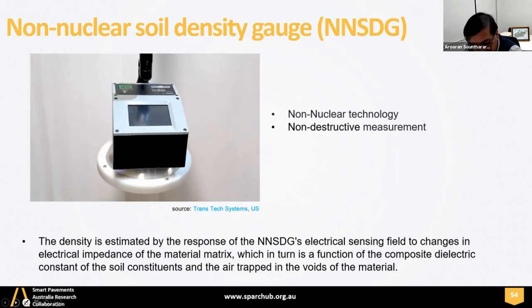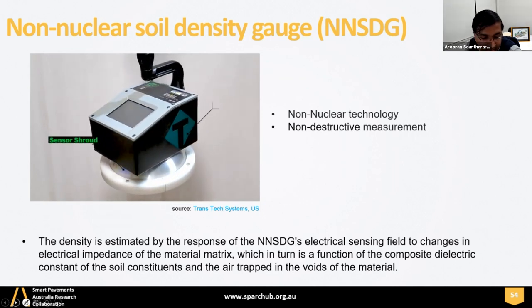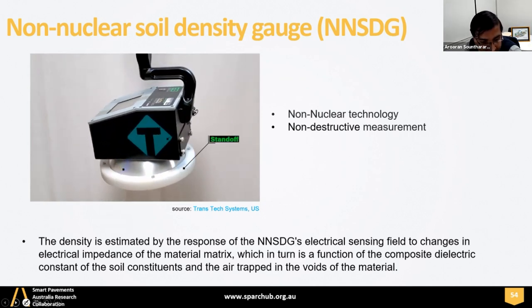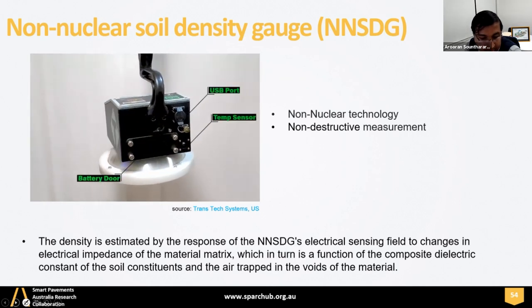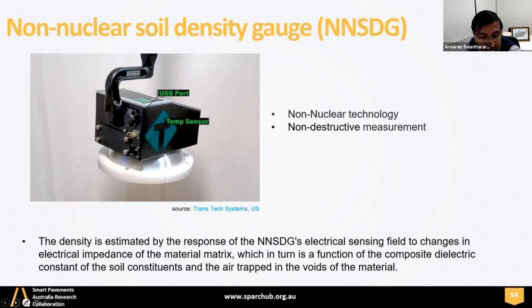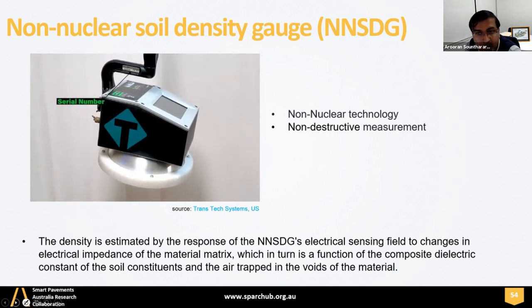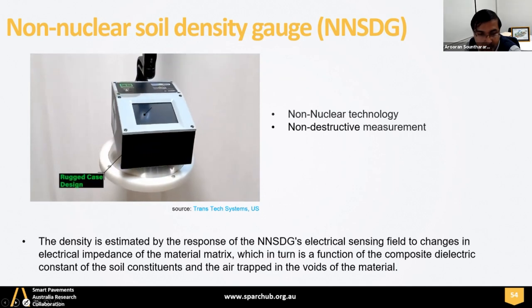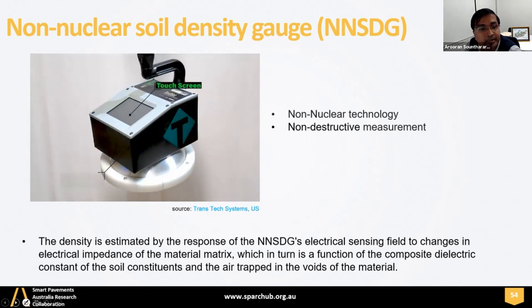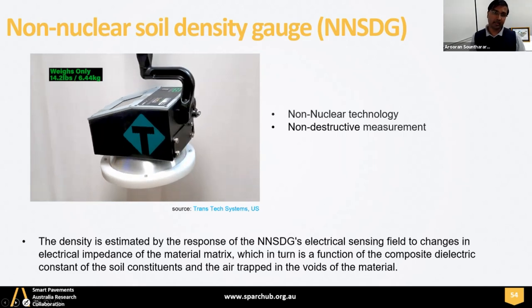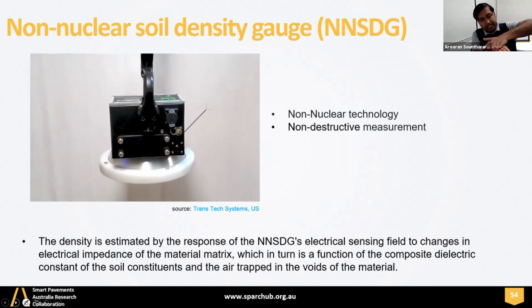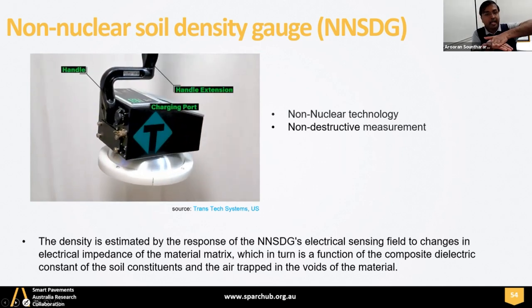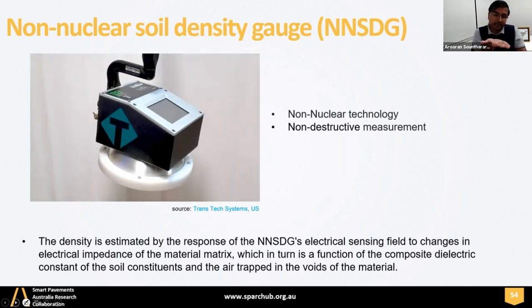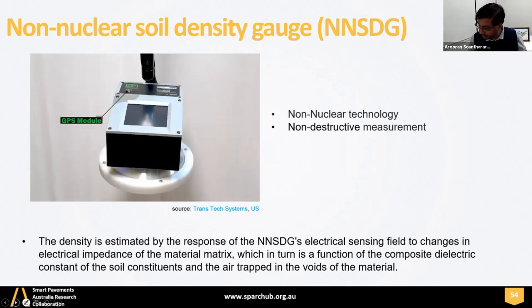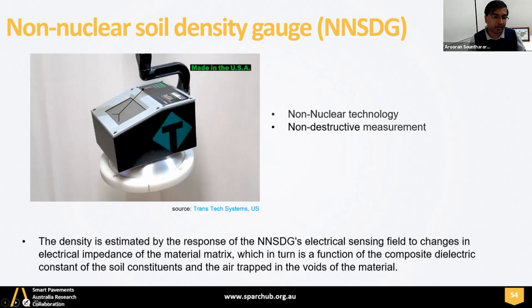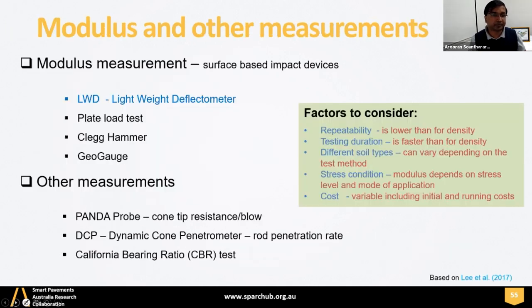So since the dielectric constant of air is much lower than that of the soil constituents, as compaction increases, the combined dielectric constant increases because the percentage of air in the soil matrix decreases, right? So this is a non-nuclear technology. That means you don't have any hazard when the test is operated. Also, it is a non-destructive measurement. That means you can directly place this device on the surface of the pavement and then you make the measurement. However, the depth of testing is limited. It goes up to 100 millimeter and 150 millimeter respectively, depending on the device you buy, right?